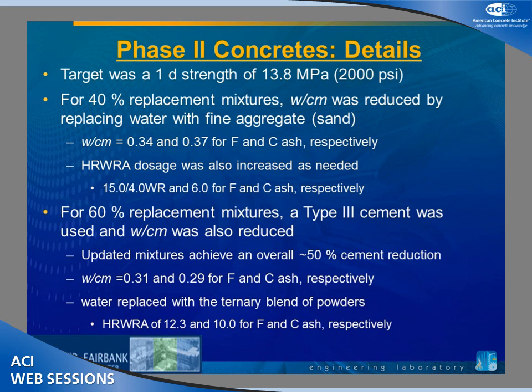So for the phase 2 concretes, we decided we needed to spec a minimum 1-day strength that we were looking for. We picked 2,000 psi. And for the 40% replacement mixtures, we decided we would just stick with the type 1-2 cement and cut back on the water. We did that not by adding more cementitious, but by replacing the water with sand. And those are the water-cementitious materials ratios we ended up with for the F and C ash, respectively. When we took the water out of the mix, we had to increase the high-range water reducer dosages, and in one case, add in a mid-range water reducer for the F ash.